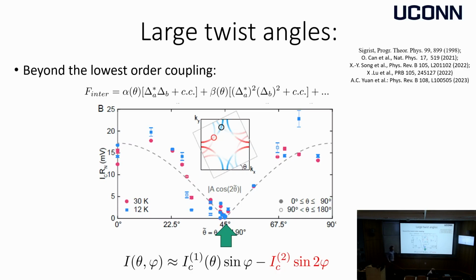So the point that is more interesting is that as you go to 45 degree, the only thing I told you, that the lowest order coupling across the interface vanishes. That doesn't mean that the higher order ones cannot be there. And indeed, these terms are allowed, and they would generate an additional critical current, so you would see some superconductivity. And the physical meaning of this term, if you wish, is the co-tunneling of two Cooper pairs simultaneously.